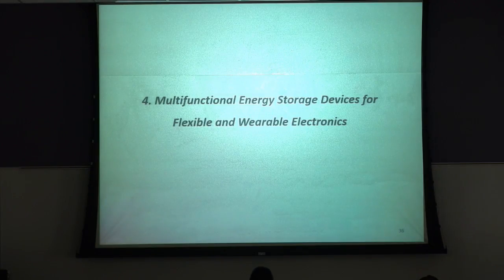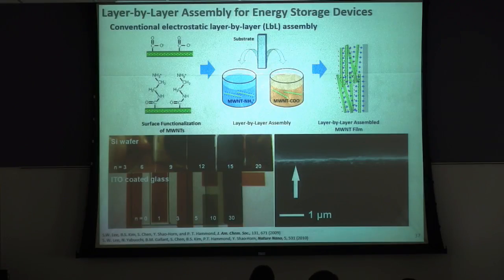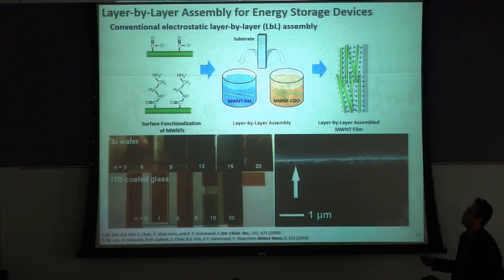Okay, so this is the last topic. Basically the last topic is the multifunctional energy storage device for flexible and wearable electronics application. So let me first introduce the layer by layer self-assembly process. Basically, layer by layer self-assembly is a thin film formation process based on the electrostatic interaction between negatively charged and positively charged species. So if we prepare negatively charged carbon nanotubes and positively charged carbon nanotubes separately as solutions, then we dip the substrate alternately into these positively and negatively charged solutions. So this kind of carbon nanotubes can be self-assembled by the electrostatic attraction.